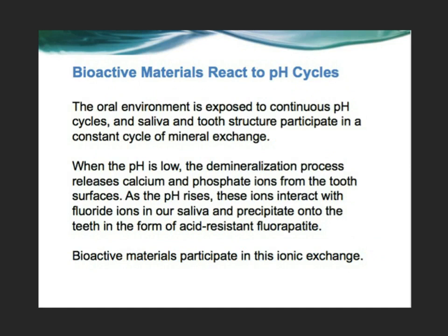Bioactive materials also react to pH cycles. When the pH is low, demineralization happens and calcium and phosphate ions are removed from the tooth. When the pH rises, these ions can interact with fluoride in the saliva and precipitate onto the tooth surface and form acid-resistant fluorapatite. This also happens internally when talking about cavity liners and bases because of the fluid and the ion availability in the dental tubular fluid.